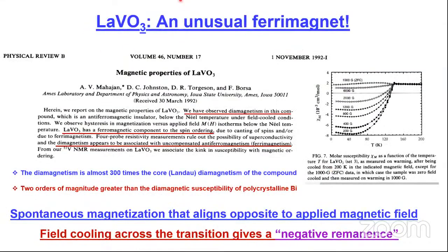Now, LaVO3 is an interesting magnet. In fact, in the 1990s, people studied this material a lot, and it becomes strongly diamagnetic if it is field cooled across 138 Kelvin. It is so strongly diamagnetic that people thought they had actually discovered a 140 Kelvin superconductor at that time. You can see that in this paper, they actually mentioned superconductivity, but of course, transport measurements showed that this is an insulator. And this diamagnetism is not coming from the core Landau diamagnetism of the compound. This is much, much stronger than that. And this is 2 orders of magnitude greater than the diamagnetic susceptibility of polycrystalline bismuth.